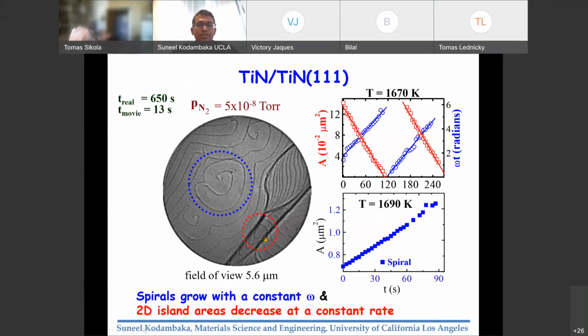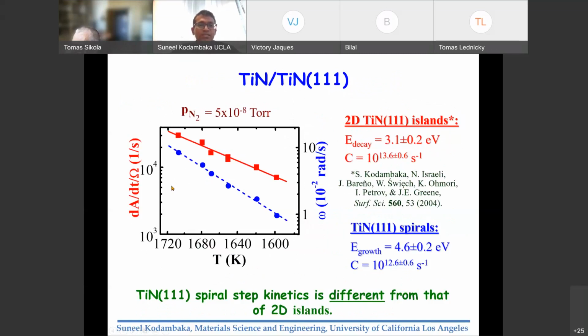To explain this behavior, we compare and contrast the rate at which these steps grow and the rate at which these islands disappear. We find that the spirals grow at a constant frequency and the islands decay at a constant rate. We can extract the activation barriers associated with the decay of the islands and the growth of the spirals. We find that the growth of the spirals is associated with a higher activation barrier of about 4.6 eV, whereas for the island decay, it's between 2.8 and 3.1 eV.